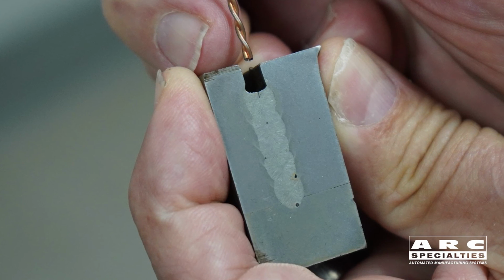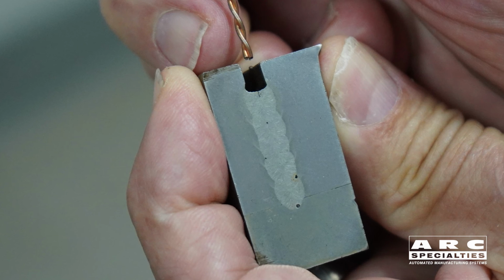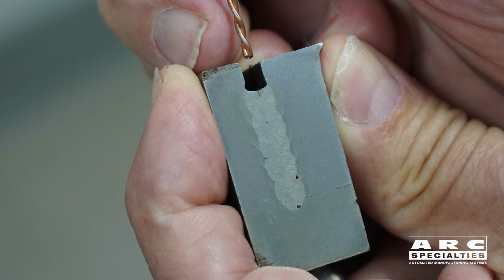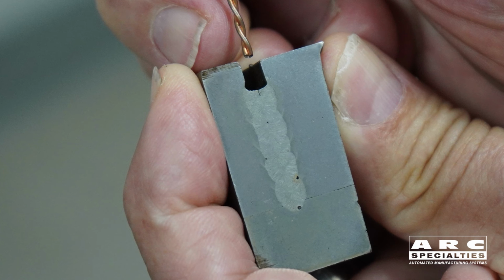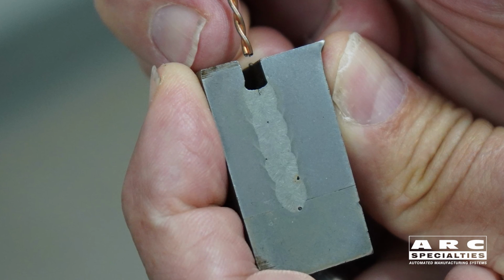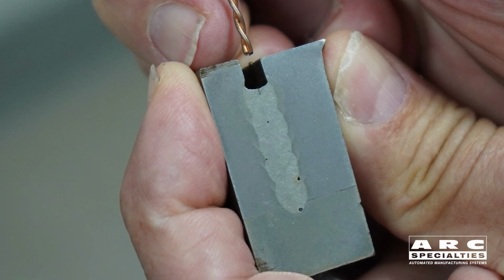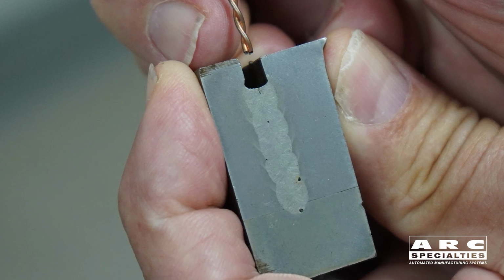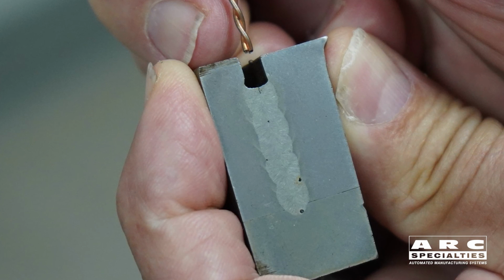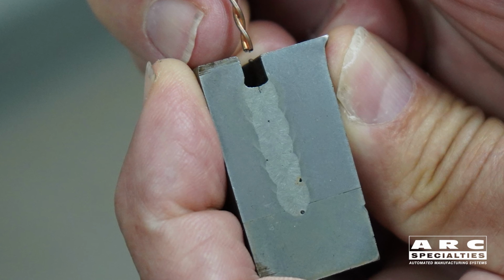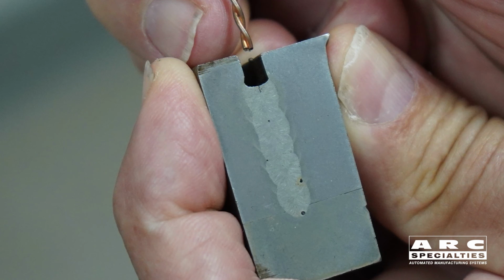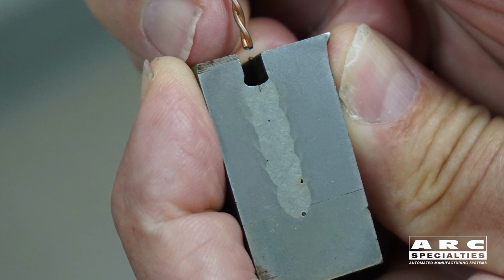I thought it was brilliant. Unfortunately, they didn't sell a small diameter wire, so with .093 wires twisted together, the minimum groove width that was efficient was half inch, and so you didn't make any savings unless you were over 2 inches in thickness. We wanted to weld something that was closer to an inch and a half, so we actually built our own wire twisting machine. We twisted two .030 wires together and were able to weld 1 inch steel.